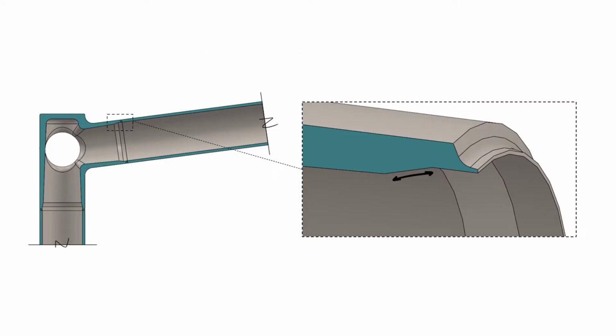Precision detailing of the cast steel nozzle ends enabled a simple CJP butt groove weld to be used rather than a more complicated TYK tube-to-tube CJP groove weld that may have been used in conventionally fabricated alternative connections. This moved the connection from a stress category DT to a stress category C1 as defined in AISC 360, offering an order of magnitude of improvement in fatigue life.